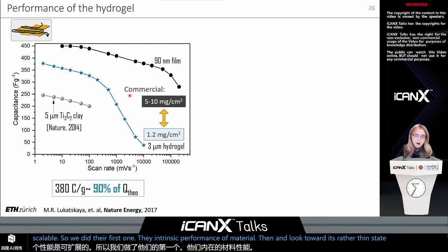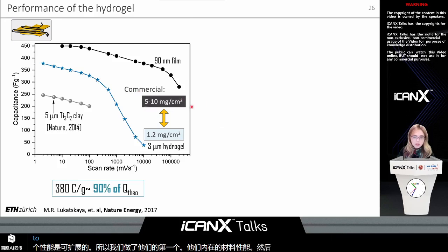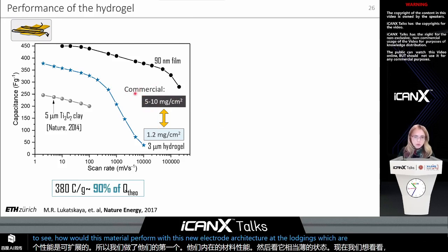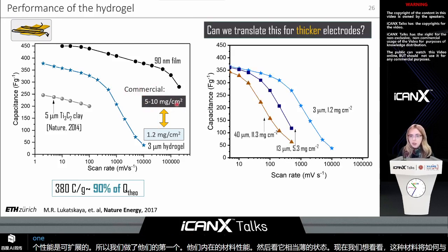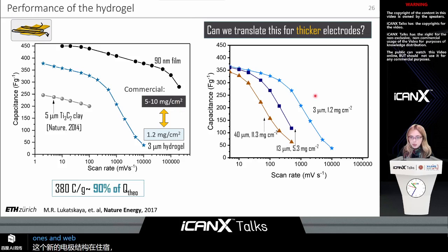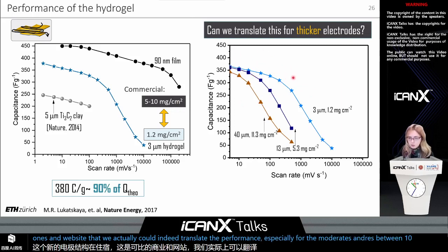And now we wanted to see how this material would perform with this new electrode architecture at loadings which are comparable to the commercial ones. And we observed that we actually could indeed translate the performance, especially for the moderate scan rates between 10 and 100 millivolts per second.